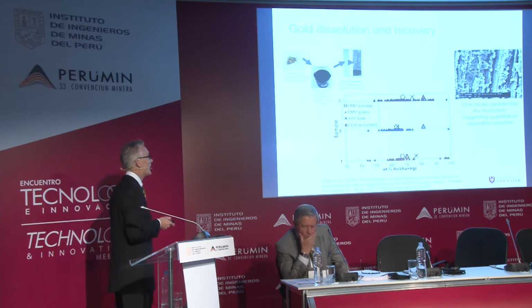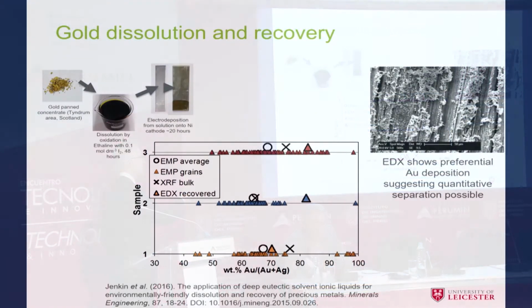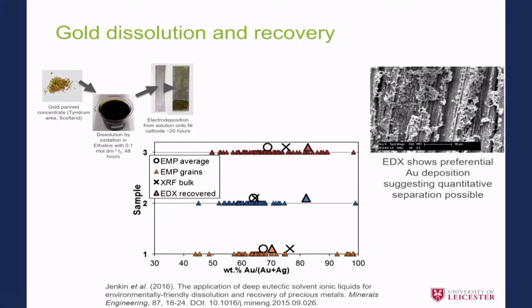Okay, here's an example of taking your gold, putting it into an iodine solution in our ionic liquid, and then recovering it on the electrode. And we can see that the material deposited on the electrode here, if we look at the filled triangles, is generally more gold-rich than the starting composition shown in the circles. Okay, so we can potentially, by adjusting the voltage, recover the gold separately from the silver.